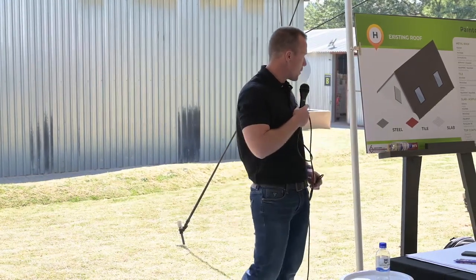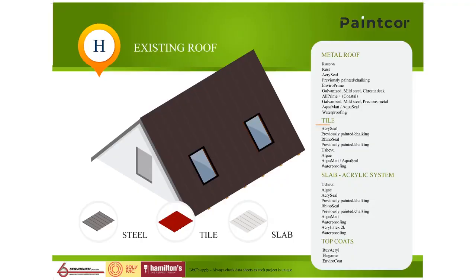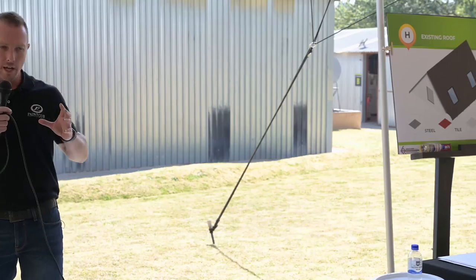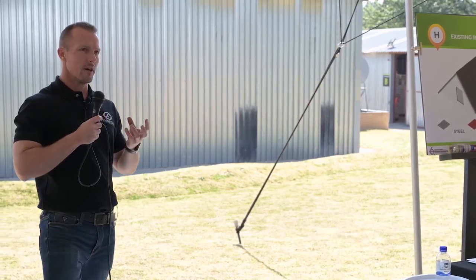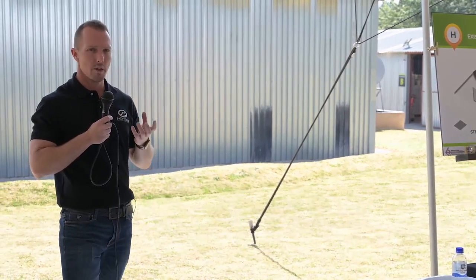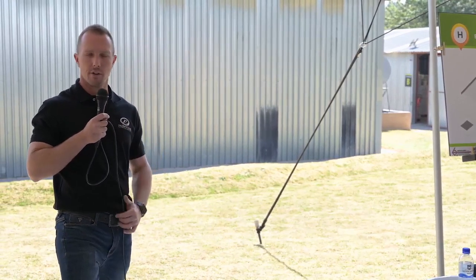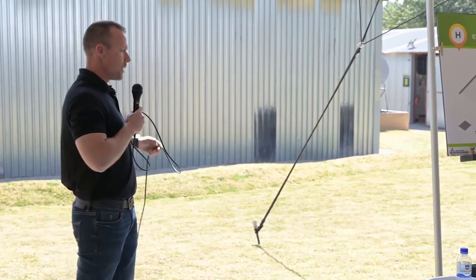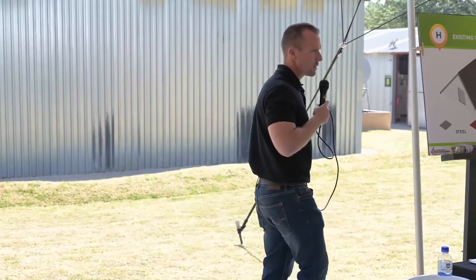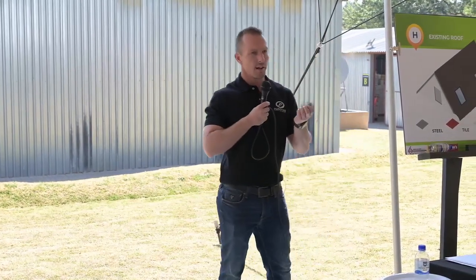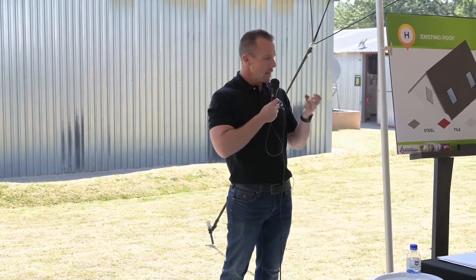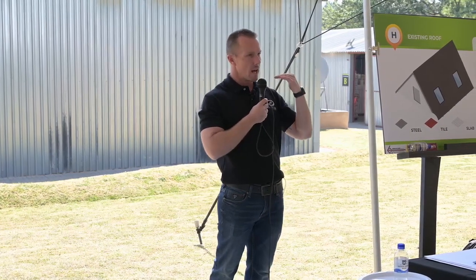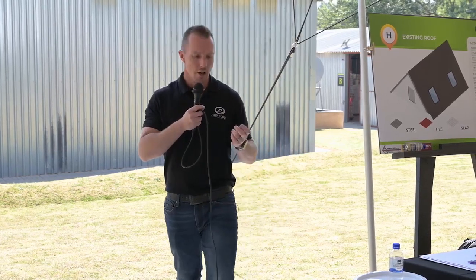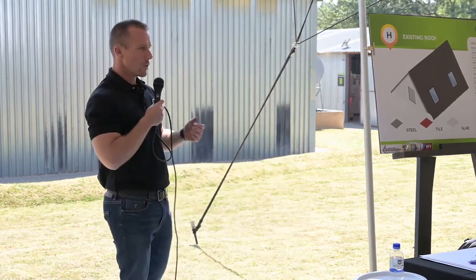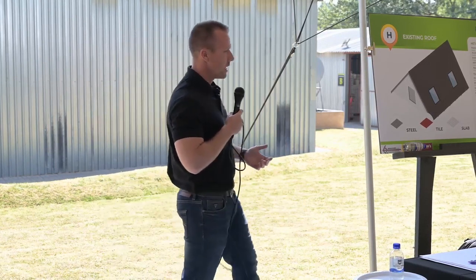The most common, or the more common one that we deal with and that we're out-speccing is your tiled roof. So that's your cement tiled roof. Remember, a tiled roof, very often the tile itself has been impregnated with color, with oxides. These are powder-based oxides, so if it's an unpainted roof and it's been weathering for anywhere from 18 months or longer, what you'll find is a lot of those oxides have now become unbound. They are no longer embedded in the actual cement tile itself. They're sitting on the surface.